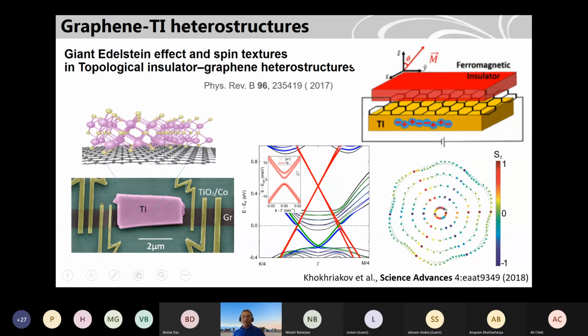And there is a theoretical idea of what should happen. You should open a gap in the graphene and get some spin textures. The spins near the Dirac point will be perpendicular, and away from the Dirac point they are more in plane. So it goes from more Rashba type to perpendicular spins. This was done in collaboration with Stefan Roche's group in Barcelona.